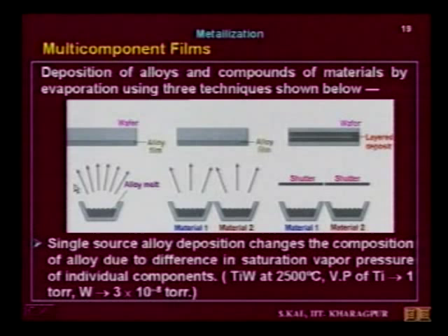That's why a third technique is proposed. What is being done here? Not simultaneous deposition, but subsequent deposition. Here they are using a shutter arrangement. Material 1 and material 2 are kept on different hearths or crucibles. On the wafer, initially say shutter 1 is open, then material 1 is deposited.